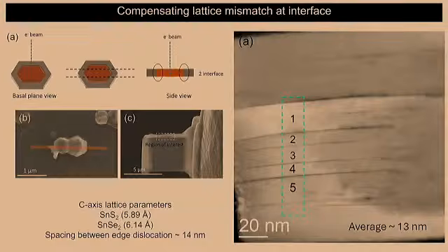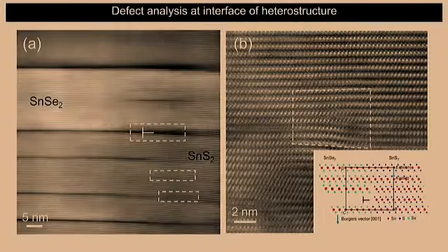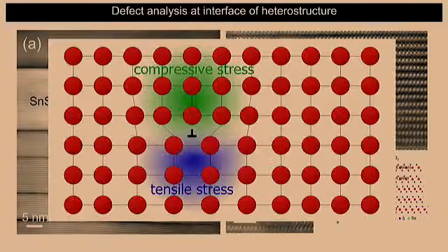If you go to a high resolution image, what we'll basically see is that we have these very nice extra half planes, extra dislocations that are coming at the interface. And the tensile part is basically, because these are weakly bonded, it basically drives cracks within these materials. Okay, so this is only possible by looking at things in cross section, right, as to what is happening at the interface here. Okay, this is exactly what is shown here.